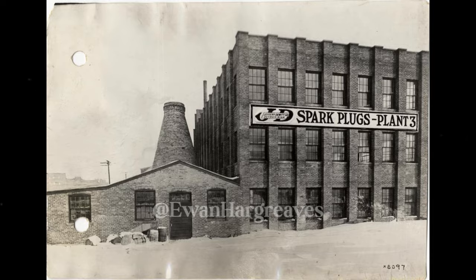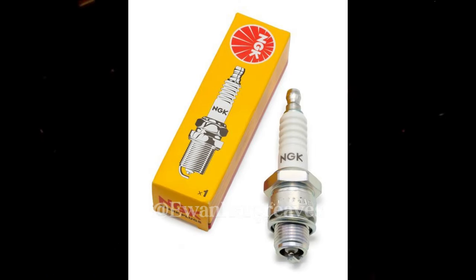Porcelain expanded too little compared to steel. That's why early porcelain insulators cracked so often. The steel shell would expand, squeeze the porcelain, and crack. Sillimanite was better, but still not perfect. Sintered alumina, its thermal expansion coefficient was almost identical to steel. As the engine heated up, the metal and ceramic expanded together, no stress, no cracking. The plug could survive hundreds of thermal cycles from cold start to full operating temperature and back, without degradation.